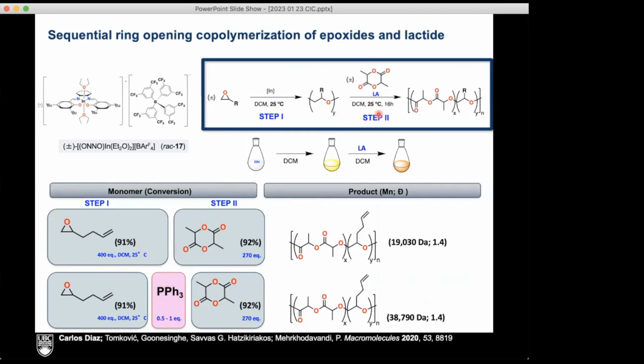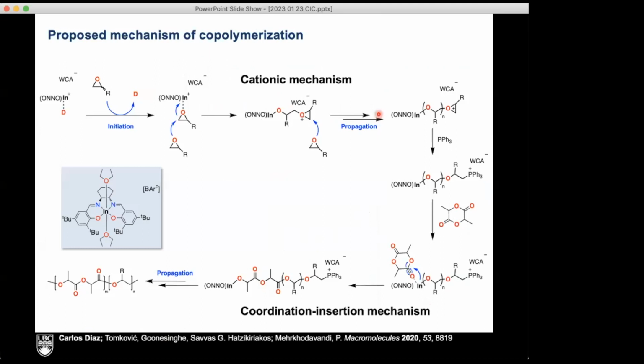And so what's happening in this situation is that he's got a cationic system. We start with the cationic indium complex, he adds the epoxide, there's a cationic polymerization of epoxide. And this is what the chain end looks like. And the nature of the anion matters because that's what stabilizes the cation. So once he's ready to finish this reaction, he adds the triphenylphosphine. The triphenylphosphine basically neutralizes the chain end here.